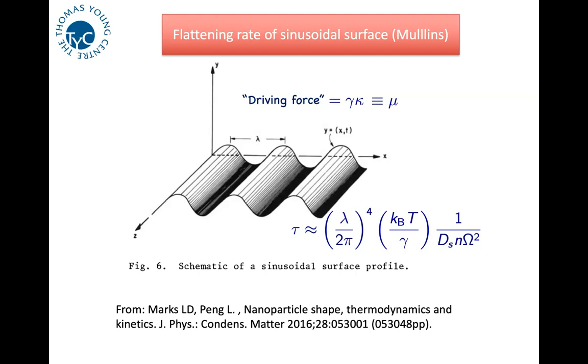I copied the picture out of a review, which says, well, suppose you have a sinusoidal corrugation of a surface with a wavelength lambda. How long does it take for that to heal up by surface diffusion? It's a nice little problem in solving a differential equation over 2 dimensions. And the time scale for that is as I've given you there: it depends on the 4th power of the length scale, lambda to the 4th, inversely on the surface energy, which you'd expect, and inversely on the surface diffusion coefficient. N there is just the density of sites on the surface. Omega is the atomic volume. So that's the length scale, and you could use that for actually making a measurement or an estimate of the surface diffusion coefficient, for example.